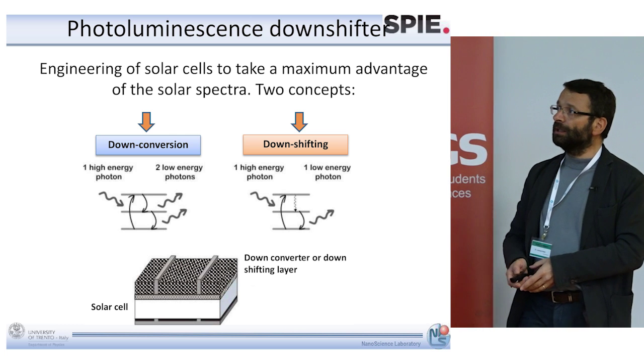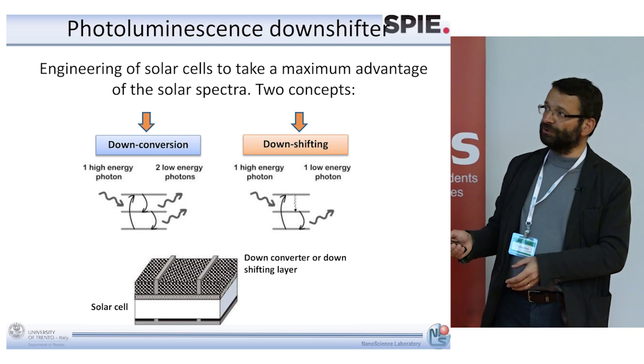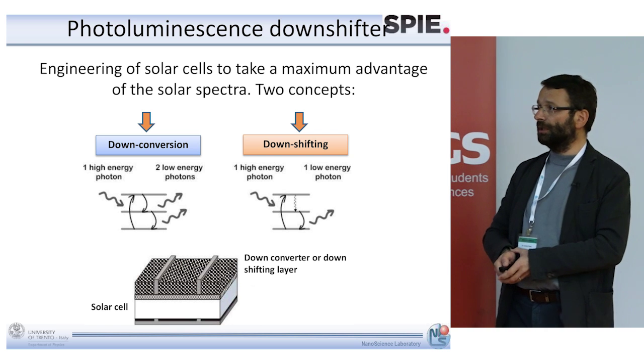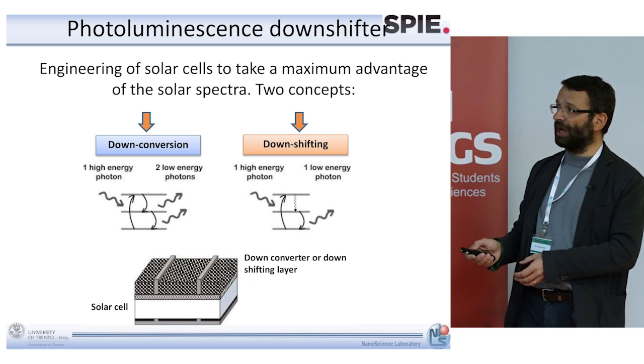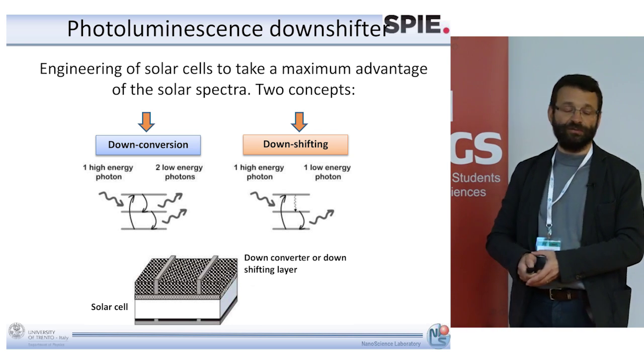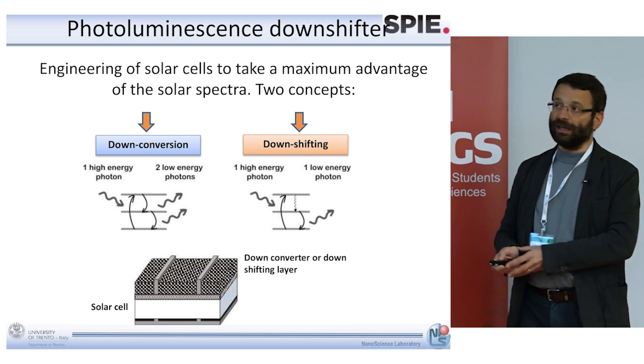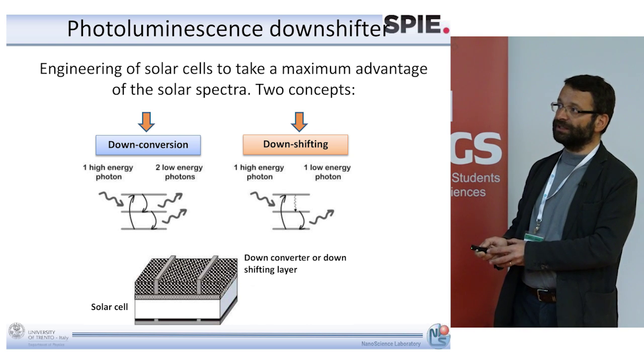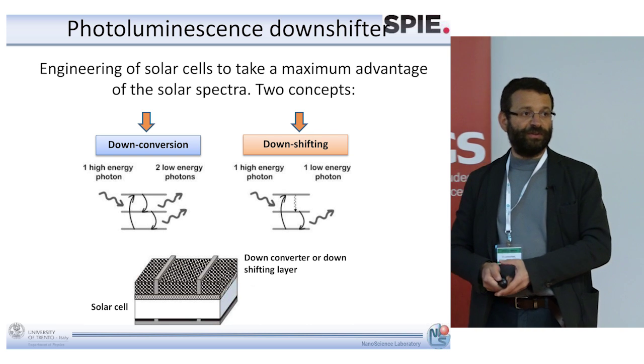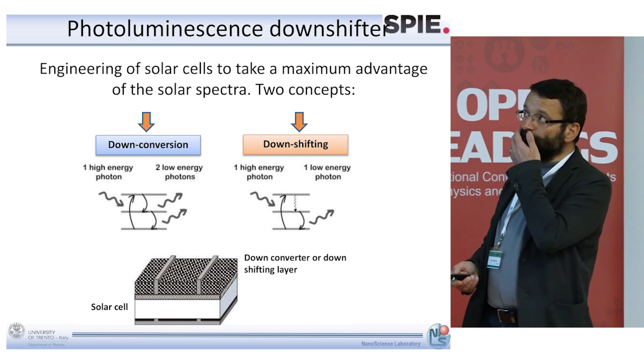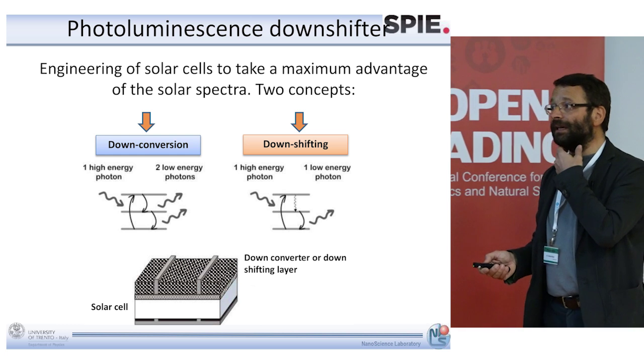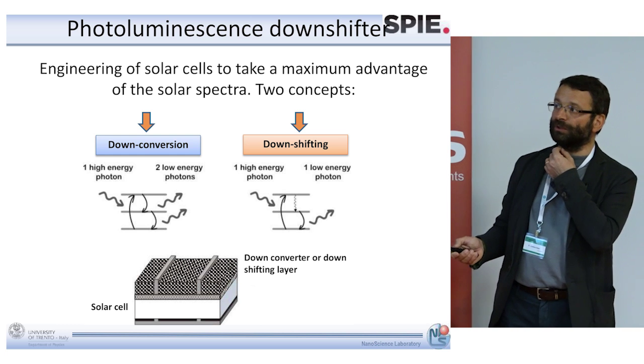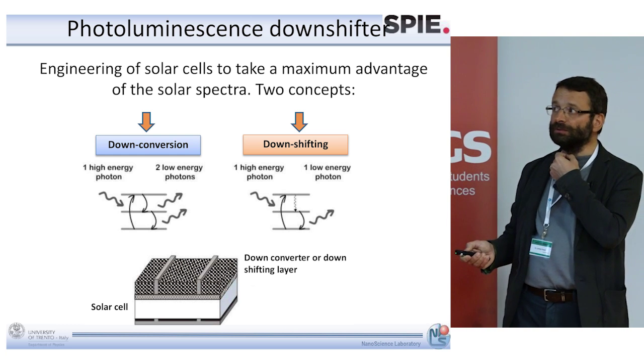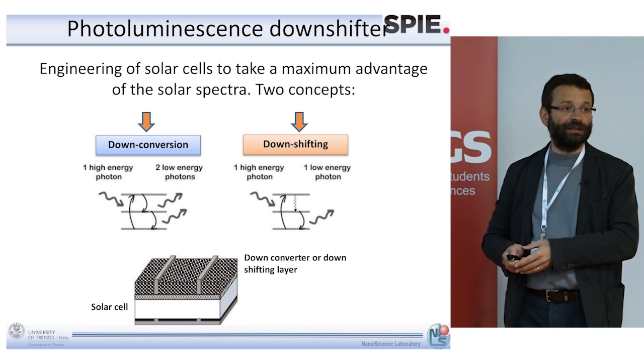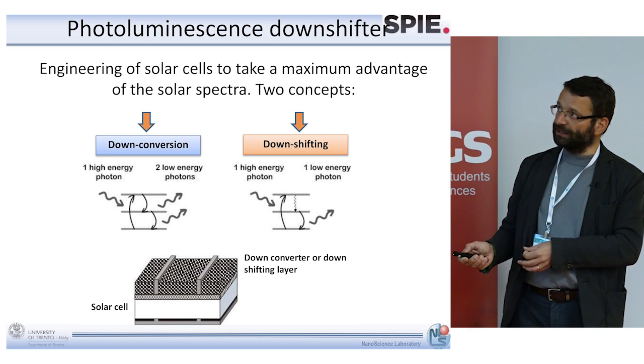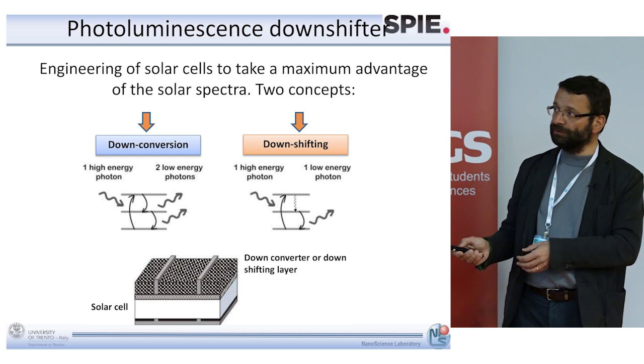And to do that, what we want to do is take high energy photons and convert those high energy photons into low energy photons in such a way that the energy difference is not wasted in heat of the silicon itself. So to do that, essentially we use the fact that in silicon nanocrystals the absorption is effective in the blue and the emission is in the red. So we want to transfer photons from the blue to the red.